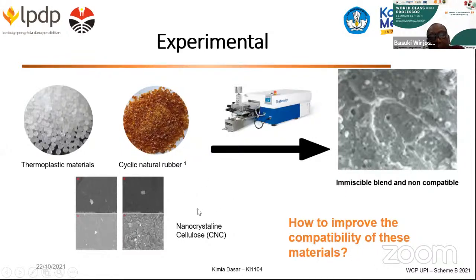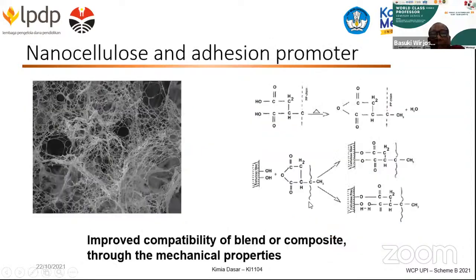So we introduce nanocrystalline cellulose, which we produce from palm oil empty fruit bunch. With the help of our friends from Girona, we produce both nanocrystalline cellulose and nanofiber cellulose. So we produce what we call an adhesion promoter. Actually, we already have commercially available adhesion promoters, two types: high molecular weight and low molecular weight adhesion promoters.